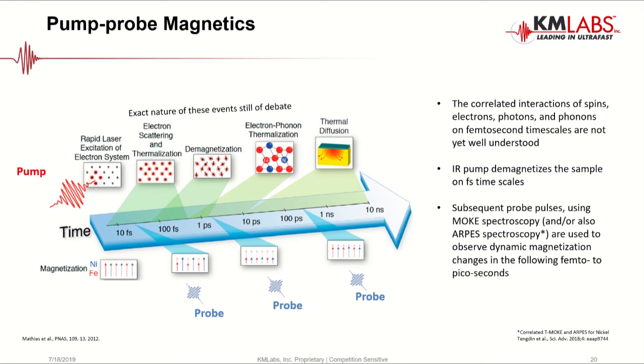We're doing this using a technique called MOKE spectroscopy, or magneto-optical Kerr effect, that's based on the idea of when you have a magnetic sample, the intensity of a reflected beam off the surface is going to change as a function of the magnetic spin state. So we can leverage this to make this kind of MOKE measurement over a series of time here following the pump and back out essentially the magnetic dynamics occurring in each of these elements.